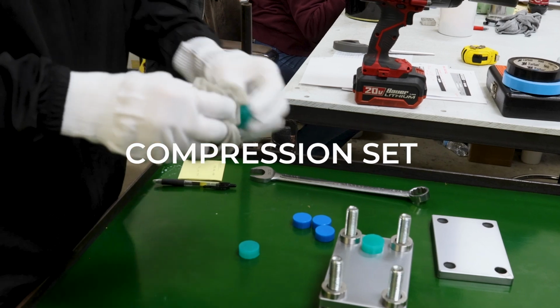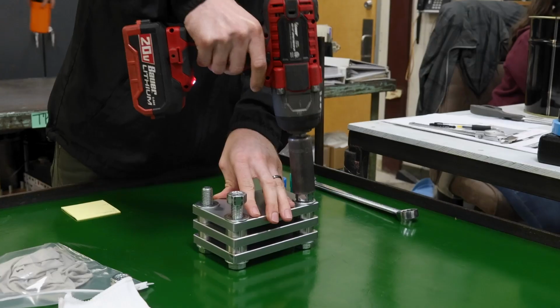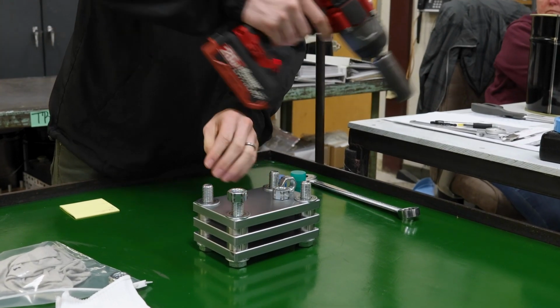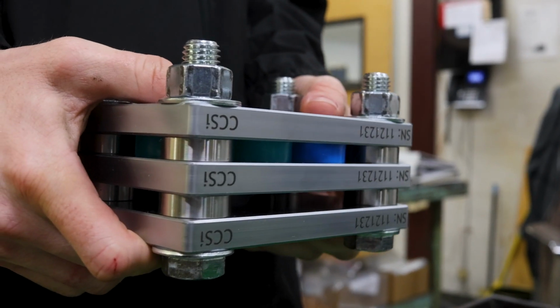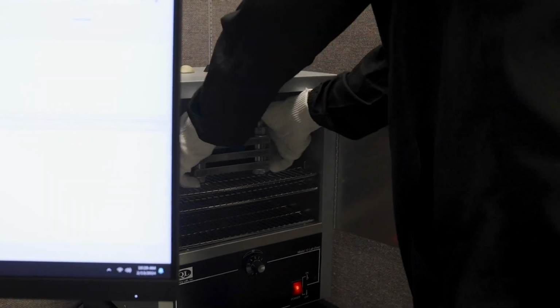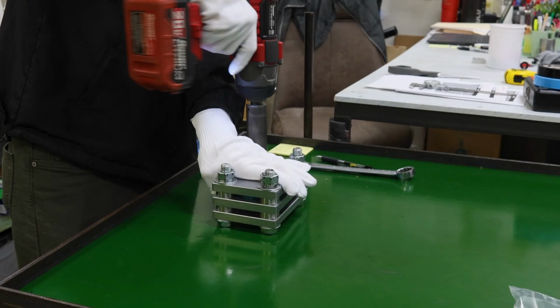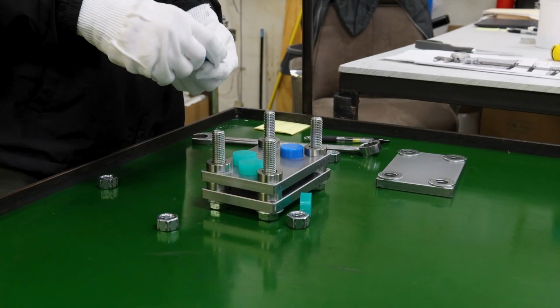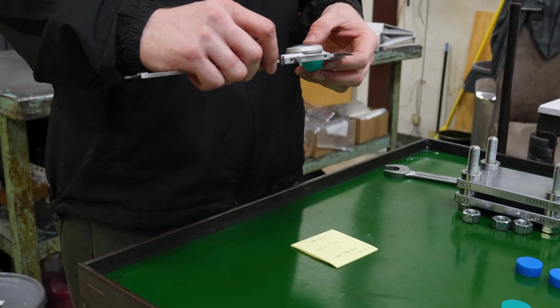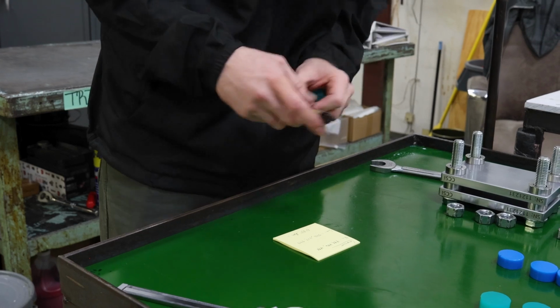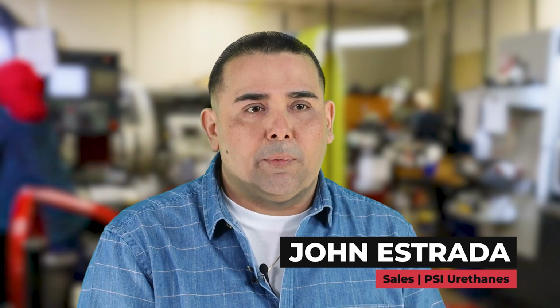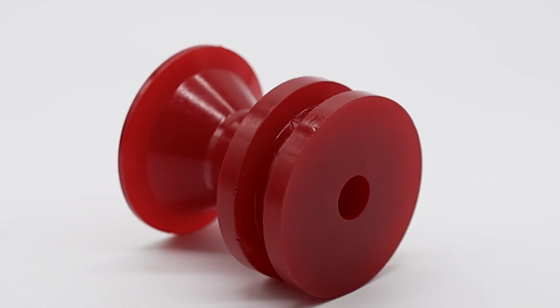Compression set is the percentage of a specimen's rebound after being compressed to a certain percentage. Our compression tests are done in a fixture that takes a 1/2 inch specimen and compresses it down to 3/8 for 22 hours at 158 degrees Fahrenheit. After the 22 hours have passed, you take the specimen out, you wait 30 minutes on a surface that is non-heat transferable, and you take your measurement, collect the data on all of those, average them, and that is your percentage. Compression set's going to come into play with the mounts, bumpers, wheels.